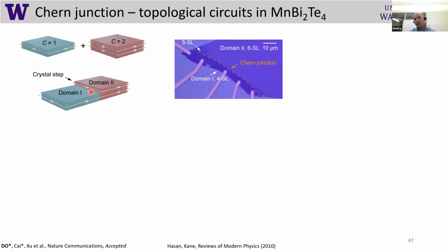And in our case, as soon as we get the samples by mechanical exfoliation, just by luck, we can get different domains in a single device or a single flake. For example, in this case, we have 6 septuple layers and 4 septuple layers, and there is an interface in between on which this Chern junction between 2 different Chern numbers could form.